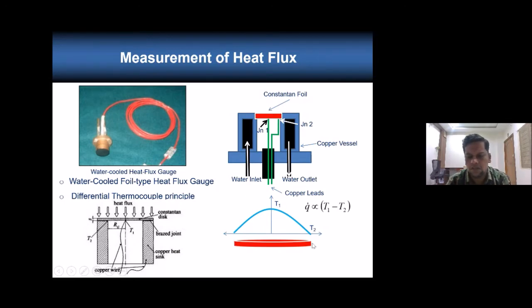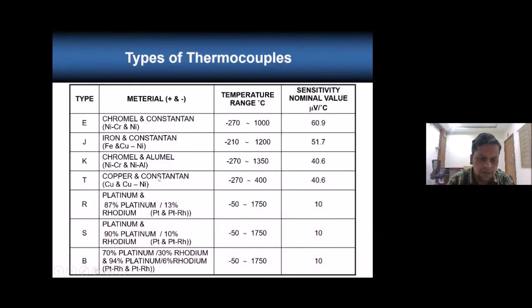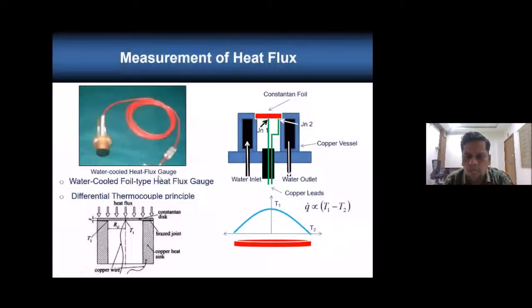This is the temperature profile over the constantan foil. This is only microns of thickness. So the maximum temperature we can achieve at the center will be around 170 degrees. So this is a T-type thermocouple. You can see one constantan and copper is a T-type thermocouple. Here we are measuring two temperatures: one is copper-constantan at the junction at the center, then copper-constantan at the edge.